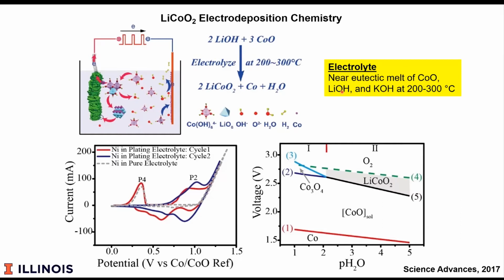And the reason for the use of the lithium and potassium hydroxide is not only to control the activity of the hydroxyl groups, but also this eutectic has a much lower melting temperature than pure lithium hydroxide. And of course, cobalt is the precursor for the system. Potassium hydroxide is not consumed, so during plating, you simply add additional cobalt and lithium as needed to maintain the stoichiometry.